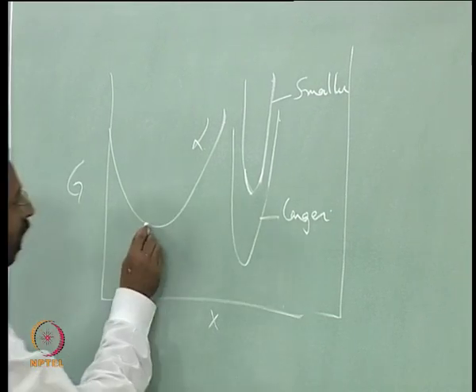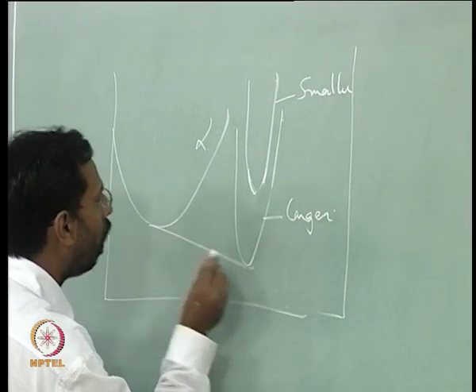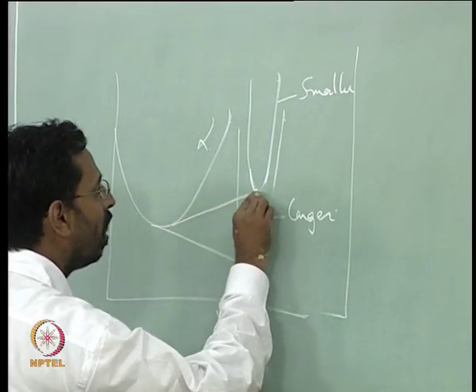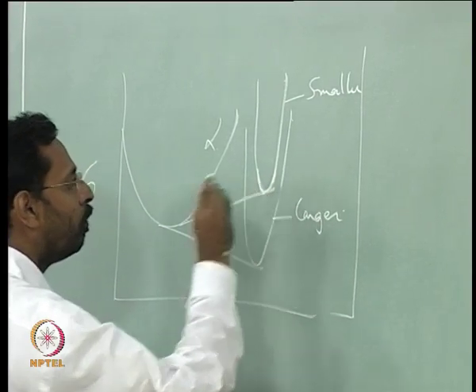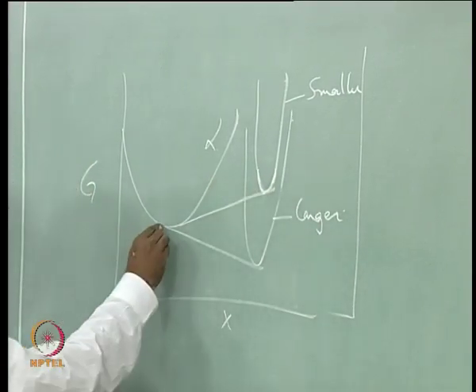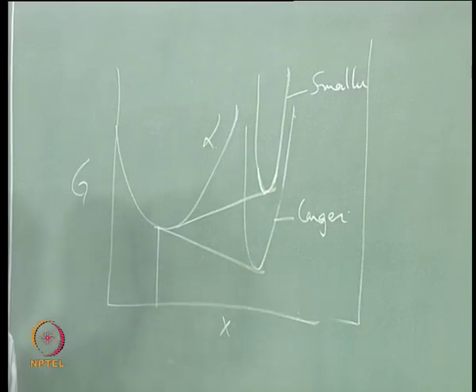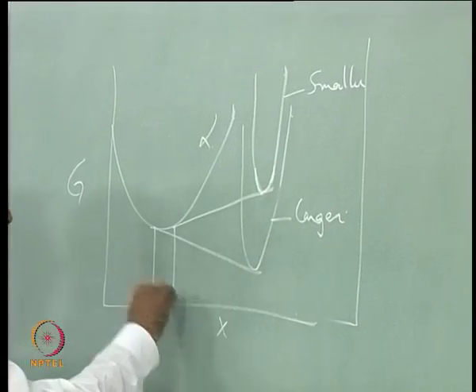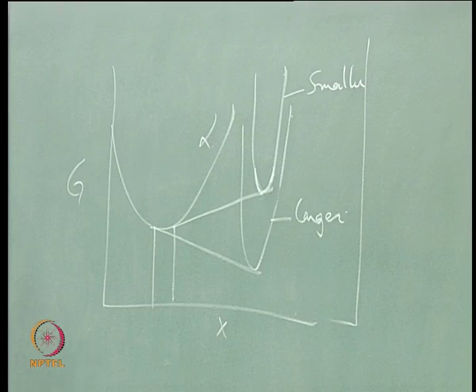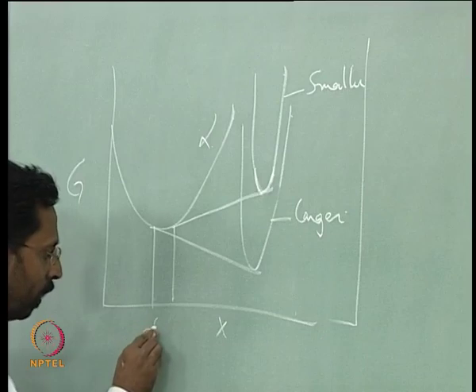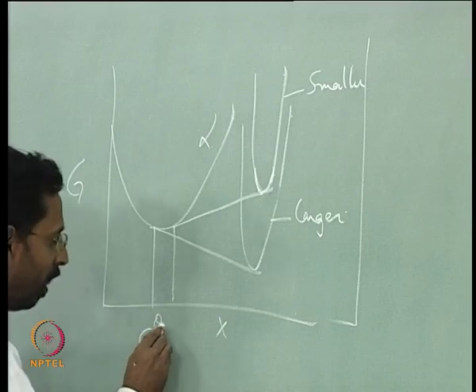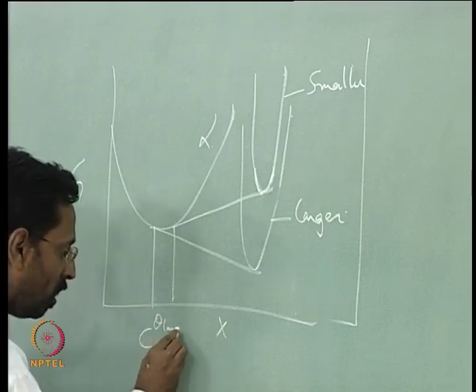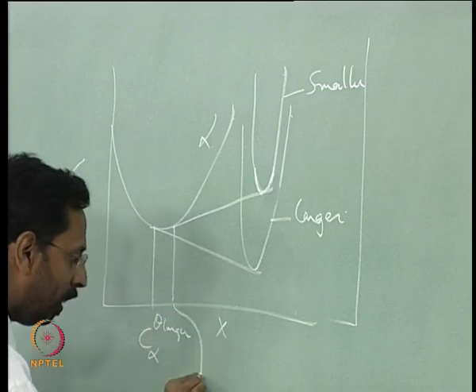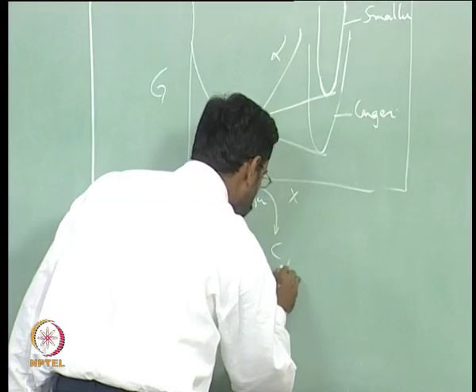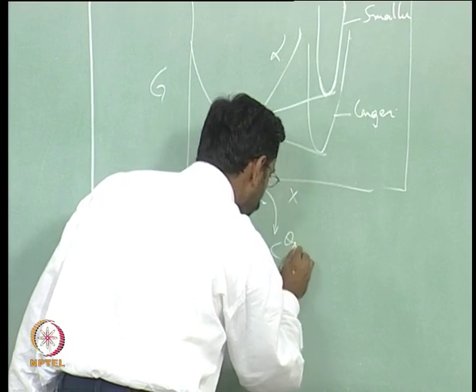So, a smaller particle will always have a higher free energy when compared to the larger particles, and if that is the case, then if I draw now a common tangent, you would see that this concept which I just now said, that the composition of alpha in equilibrium with a larger particle is different from the composition of alpha in equilibrium with a smaller particle. So, this is the composition of alpha in equilibrium with theta, which is larger, and similarly this is the composition of alpha in equilibrium with theta, which is smaller.